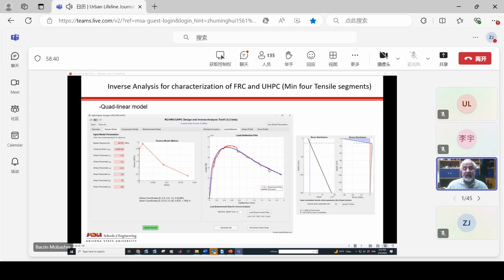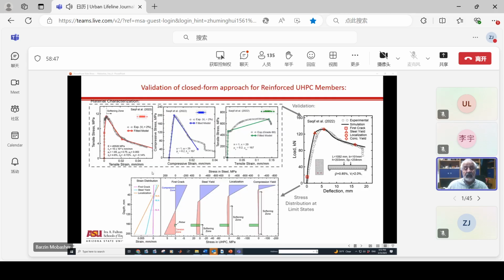If you have experimental data, what you can do is fit this curve to the experimental data and actually get your tension model and compression model. And I can show that here. So for example, this is for a UHPC member. This is out of a paper in ASCE. This hasn't been published yet, but basically what it does is that we can do the fitting of the tension, fitting of the compression, fitting of the steel, and then build up these 3 models to actually simulate the results of a reinforced concrete beam that has been made with 2% fiber and a rho of 0.85%.